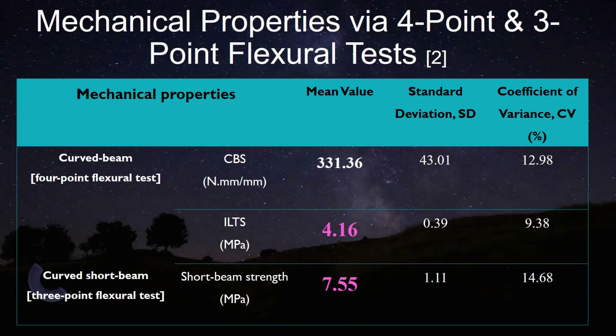And then, because that calculation is a little bit complicated, adhering to the anisotropic beam theorem, we did the short beam test, which is pretty easy through a 3-point bending, which is pretty conventional as well. But there is a limitation for that. So we found 7.55 megapascal. So these are actually convincing results that gave us hope we can go further.